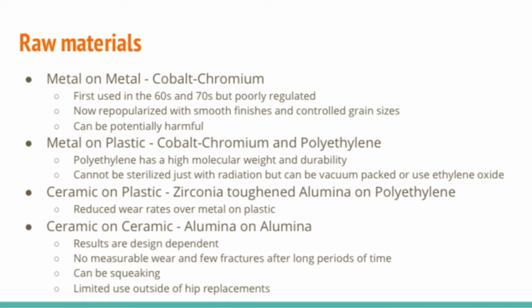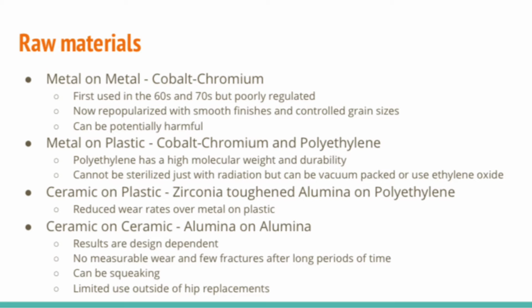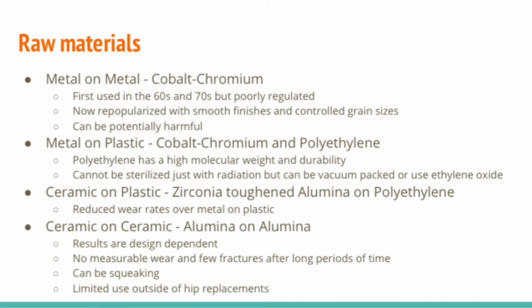The parts are now sterilized in vacuum or with inert gases present instead of air. Radiation can also be avoided by treating polyethylene with ethylene oxide or gas plasma instead. It is better to use the altered radiation method because it increases the cross-linking, which will decrease wear down the line. Zirconia toughened alumina and polyethylene has less wear than metal on polyethylene. The ceramic is very hard, but it is brittle, which means it could fracture. They have been improving ceramics by increasing chemical purity and reducing the grain sizes.